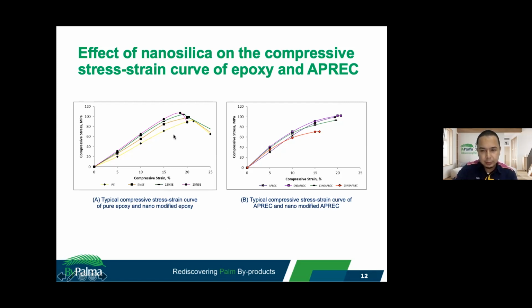shows the lowest curve. However, the pure epoxy specimen shows the highest compressive strain before failure, and then followed by the specimens from low weight percentage to higher weight percentage.